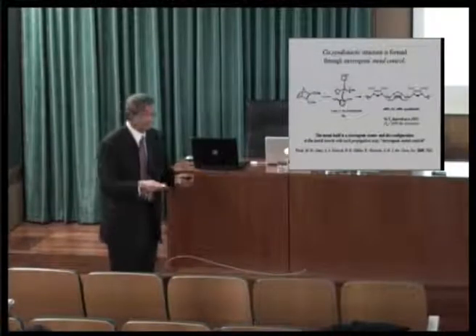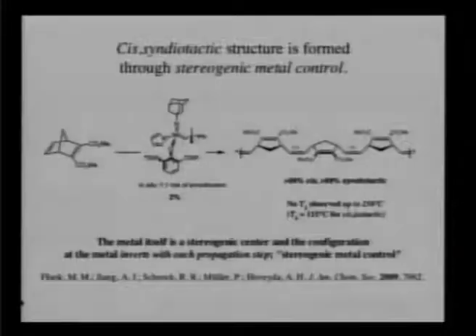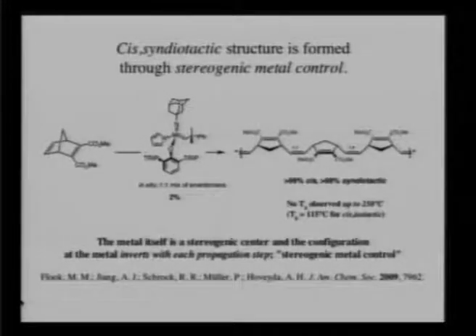Or we predicted that, and it turns out to be true. So greater than, with this large, small combination again, you can make polymers that are all cis and that are syndiotactic with these rings pointing backwards, forwards, backwards, and forwards. Now we can make the cis isotactic with all these rings pointing the same way using a biphenolate or binaphtholate catalyst and show that they are different polymers, entirely different polymers.